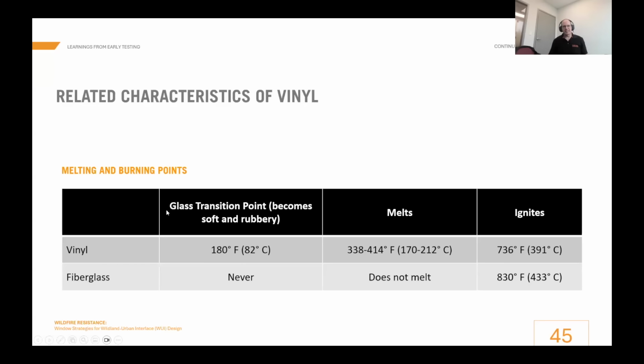Fiberglass is quite different at the practical level here. It doesn't have a glass transition point. It will never become soft and rubbery. It cannot melt. It'll ignite at a slightly higher temperature than vinyl, but it will ignite and it will burn just like vinyl. And full disclosure, the temperatures experienced during this testing on the outside surface of the windows were way beyond these ignition temperatures. So this is not a test of whether or not the frames will ignite. The frames will ignite for sure.